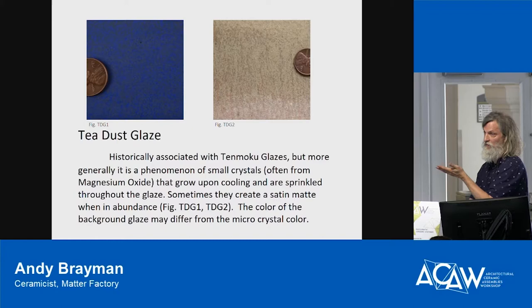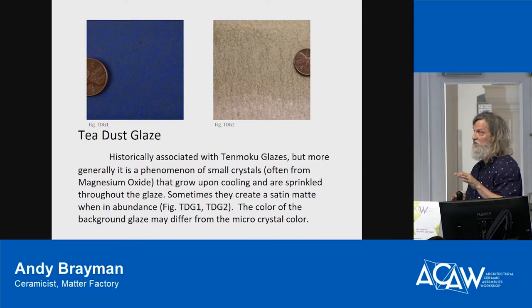So these types of glazes are going to be less reliable than a flat, glossy black. They just are, because we're talking about the growth of a crystal, which is dependent on the cooling cycle, so maybe where it is in the kiln. Stuff in the bottom right won't be cooling the same as the stuff at the top. And so some glazes that might look incredible on a 4x4 inch tile, when you scale up, you see, oh wait a second, we're not getting the same surface everywhere. Why are we not getting the same surface everywhere? They're not being careful enough.